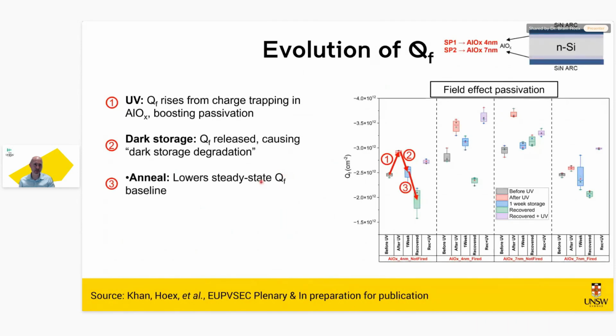Reduce in passivation. The anneal, counterintuitively, this actually reduces QF. And this is also well known for people like myself who have spent more than enough time on the AlOx system: if you anneal the system for a longer time, you typically end up with a lower fixed charge density, but you fix the DIT, so overall your passivation goes up. And a short UV dose is again enough to increase QF.